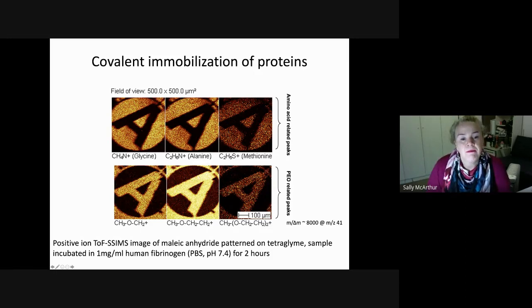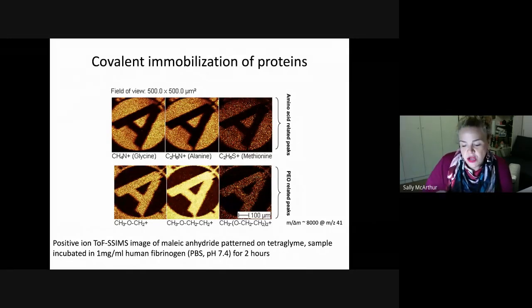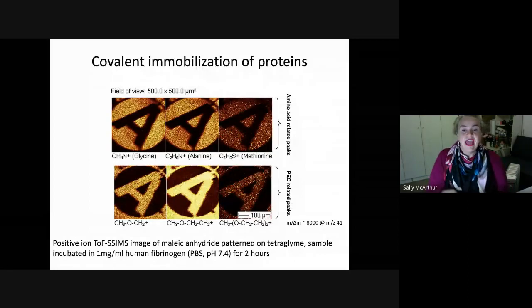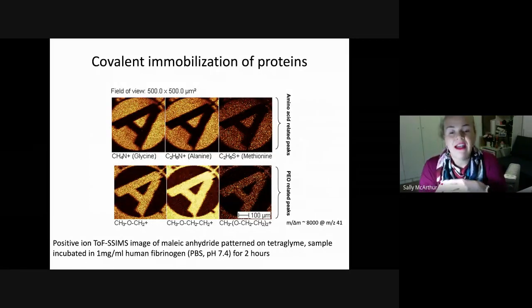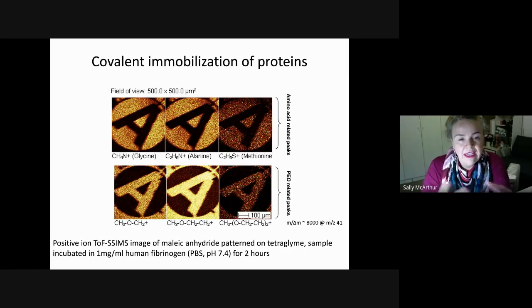And then in the bottom frame, where the A is highlighted and the outside is highlighted, these are the peaks that are directly related to the tetraglyme plasma polymer, and they indicate that there are no proteins attached to those areas. So where the non-fouling surface is, it is still non-fouling, and where the anhydride-containing region is, the protein is actually immobilized. So it's a functional coating, enabling us to actually pattern both the chemistries and control where proteins go.